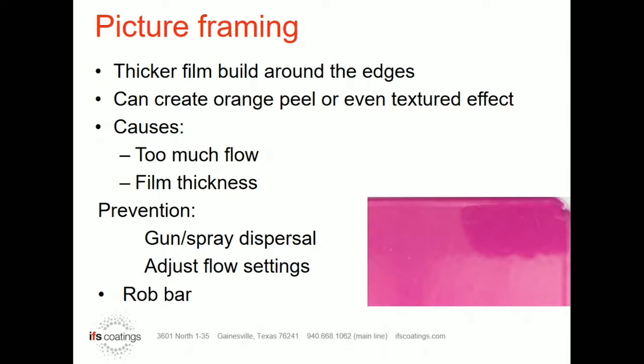One thing that might help, obviously, if you have a lot of heavy film build on the edges, my first recommendation would be to turn your KV down and turn your powder flow down. If you don't have enough film build everywhere else and you can't turn the powder flow down, then obviously turn the KV or even the microamps down, so you're not building so heavy in some of those easier to coat places.